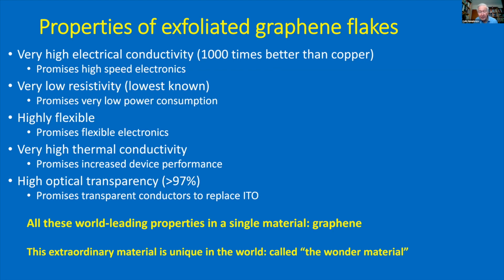And I used to work in gallium nitride, and gallium nitride power devices can only operate at about a third of their theoretical limit, and indeed experimental limit, because of the heat that they generate. And so they just get too hot and it can't be conducted away quickly enough. So increased thermal conductivity enables you to have power devices which you can get the heat away from.